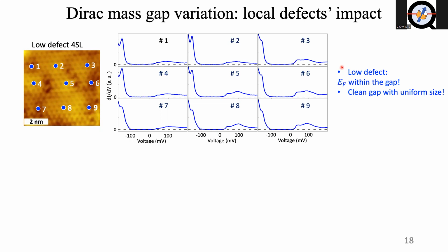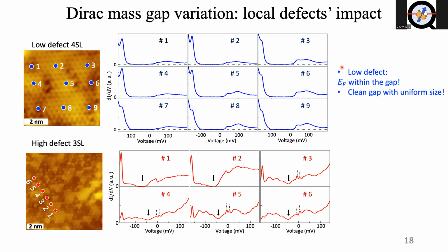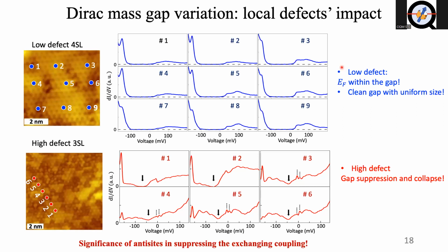However, this feature changes drastically when we go across a high defect sample. This figure is a 3SL high defect sample. When we draw a line cutting across from a locally defect free region, as represented by point number 1 and point number 2, to a highly defective region, as represented by point number 6, we can see the evolution of those spectroscopy. At the locally defect free region, we still see a finite but shrunken gap. But when we progress to the defective region, you can see the gap was suppressed and eventually collapsed. Accompanied by this collapse is a linear V-shape kind of feature. So we can conclude that in the high defect region, the gap can be suppressed or collapsed. And this points to the significance of anti-sites in suppressing the exchange coupling.